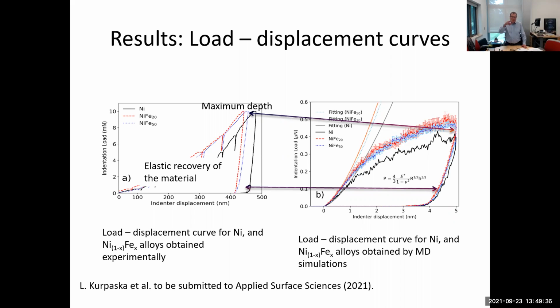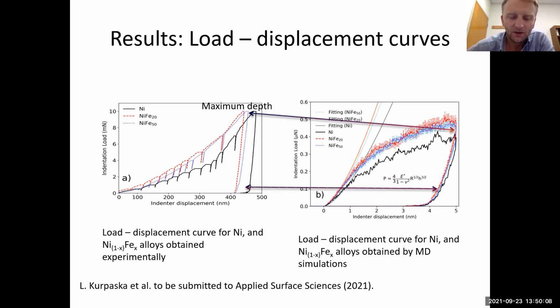And related to this, there was something I didn't understand in the experiment. Is the tip experimentally moving at a constant velocity, or are they increasing the force? No. Lucas, could you please help me with this? Yes, no problem. You can hear me. So the velocity of the indenter is constant, and we are increasing depth with each indentation. So here, this load displacement curve actually represents 10 indentations, 10 or 11, something like that, made in the same spot with increasing force.